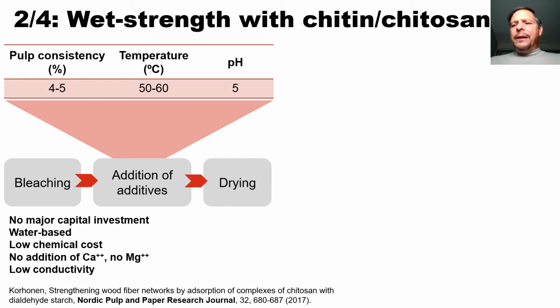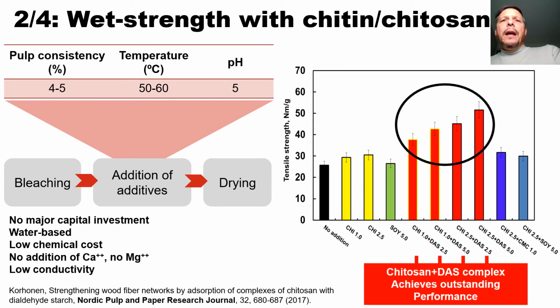Nevertheless, I want to say that in this particular case, chitosan products fare quite well as a paper making additive. In particular here, what we have found is the possibility of using chitosan to increase the tensile strength, both the dry and especially the wet strength. And for that, of course, we can use chitosan alone, but in this figure that I'm showing here, I indicate the case of chitosan alone, also with soy proteins and with dialdehyde starches. And that last combination was really the one that produced a really great performance, not only as far as the dry strength, but also as far as the wet strength, that, as you know, is a very important property in the case of tissue papers.